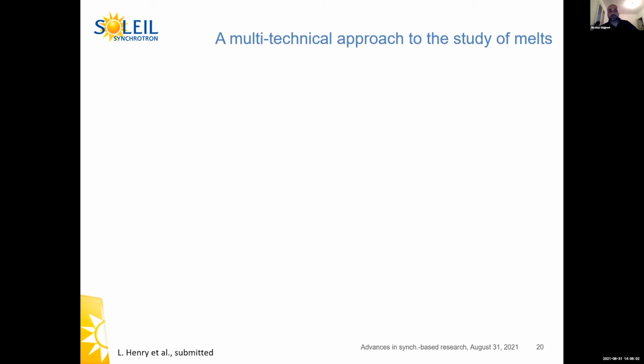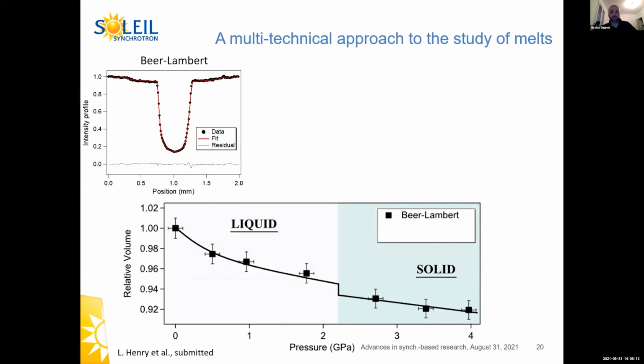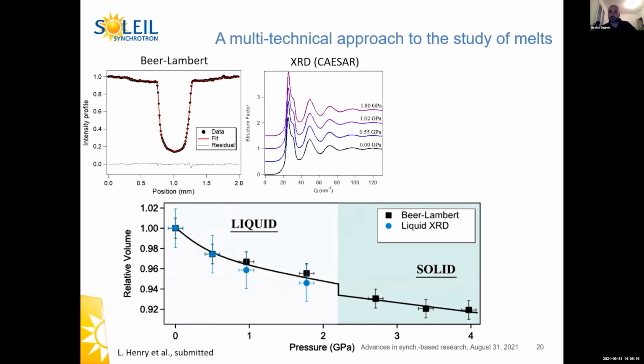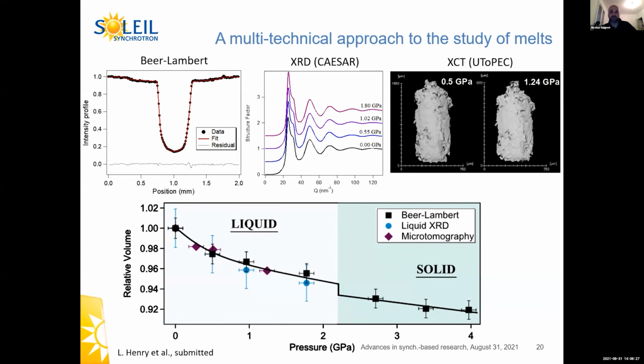Another benefit is the multi-technical approach to the study of melts. Laura did the measurements of the density of the gallium using the Beer-Lambert law I just mentioned, but also did the measurements using the X-ray diffraction from the CESAR, using the Eggert formalism that I presented earlier, so completely independent measurements. And another independent measurement is the measurement of the full volume of the sample using high-speed tomography. So three totally independent measurements of the density, and you see that the data is pretty consistent.